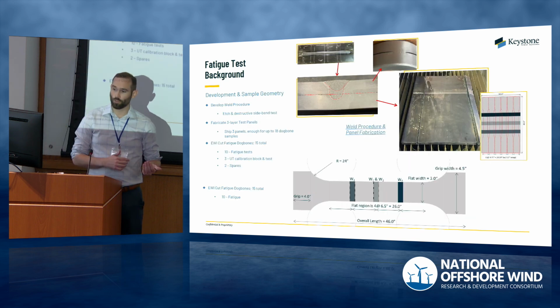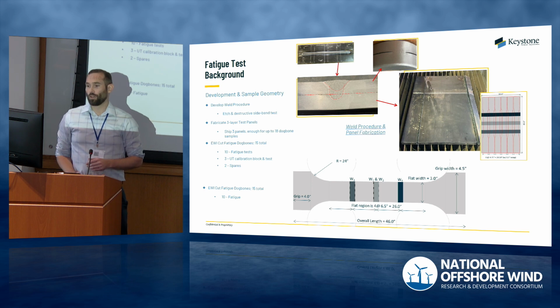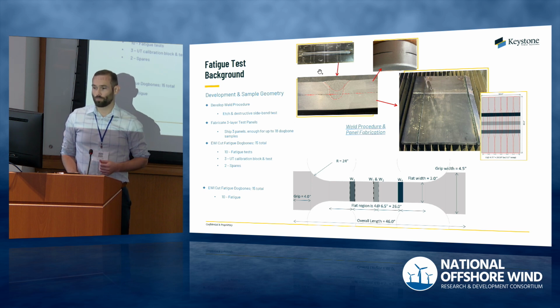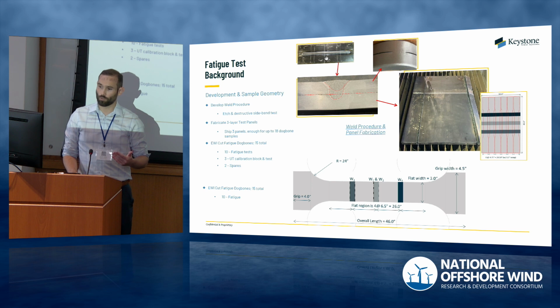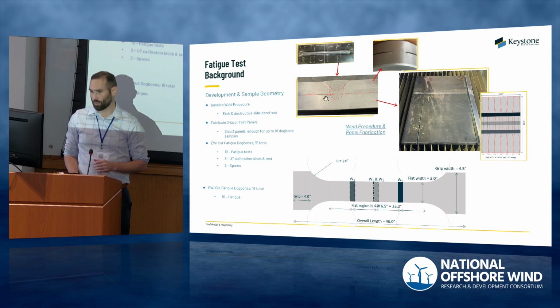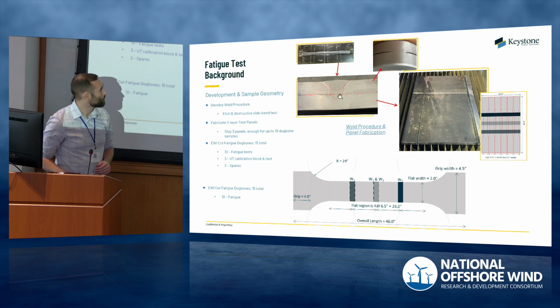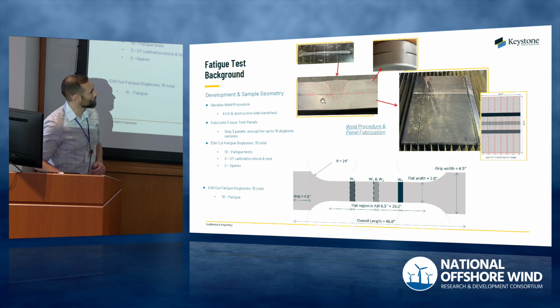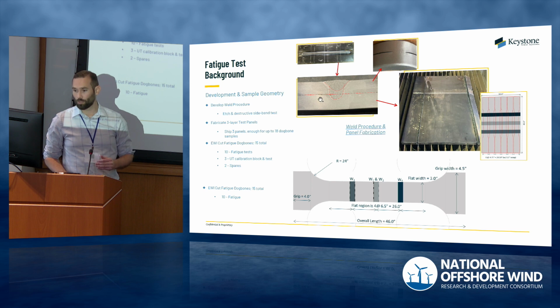So I'll talk some more about fatigue. So again, this NOWRDC funding has enabled us to develop a multi-layer weld procedure, which I show here. You can see I put in some dashed lines to show the layers, which are not very easily discerned otherwise. So this actually is not a monolithic piece, it's two layers. This was a V joint butt weld that was welded into a continuous bottom layer as backer.